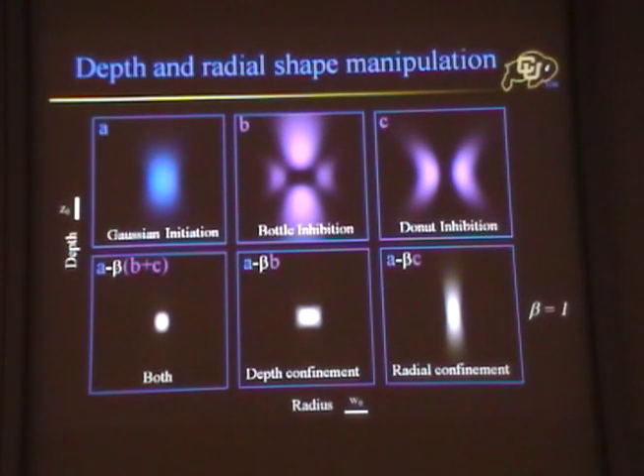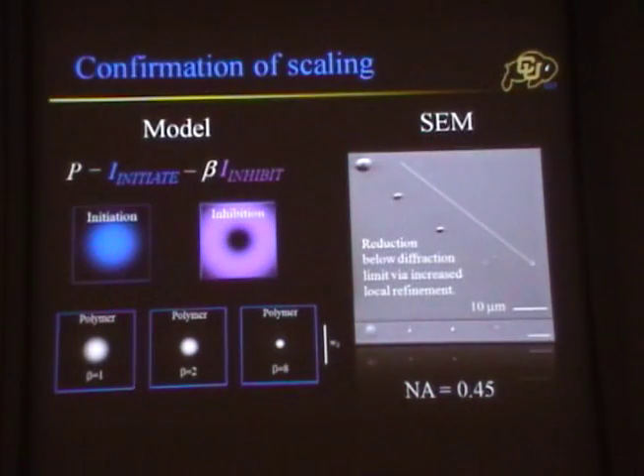And I have two polarizations at hand, so I can actually put them on both simultaneously. And for doing 3D lithography, this is starting to look like a pretty exciting little blob of material response. And by golly, it works. So you put this on a slide, you do the exposure with both colors simultaneously, then you move and write a dot because you're doing the resolution tests. Then you turn up the UV, which is basically increasing beta here, because these are normalized intensity profiles. You do it again, and that makes the donut hole smaller.